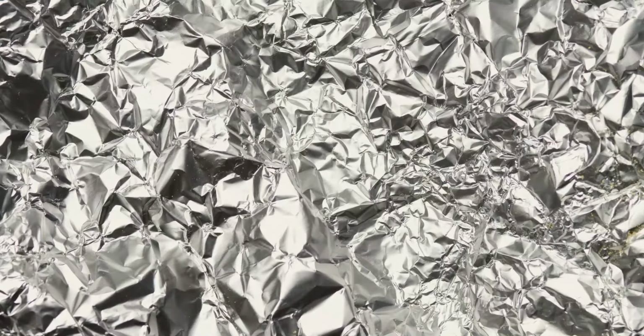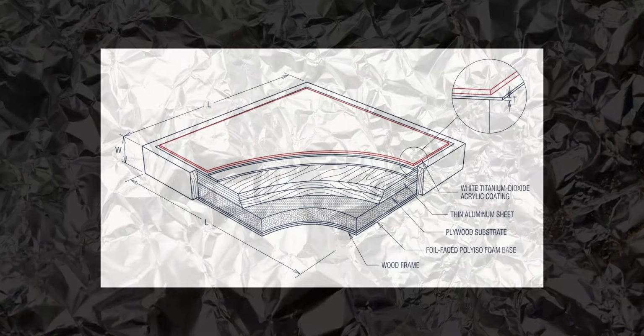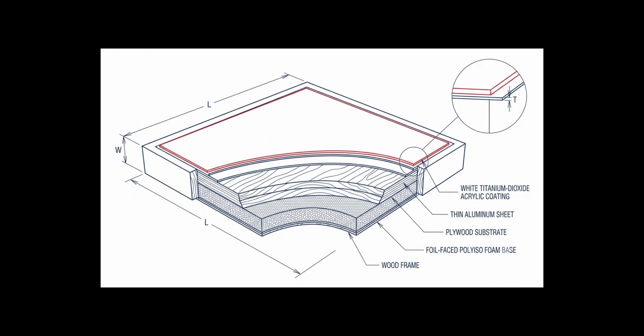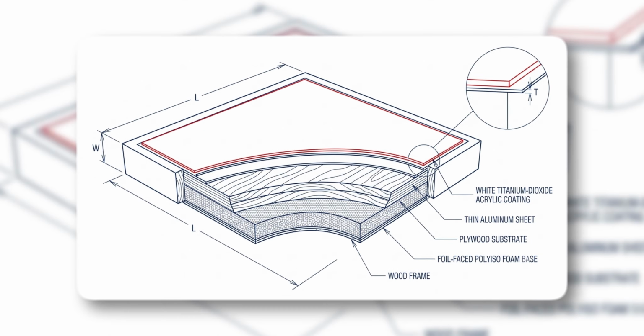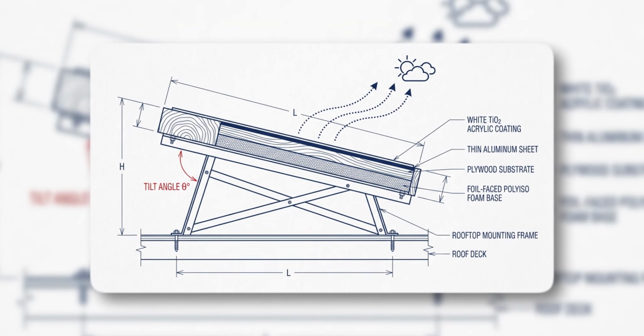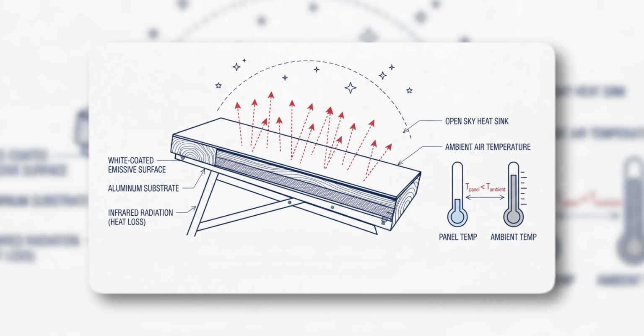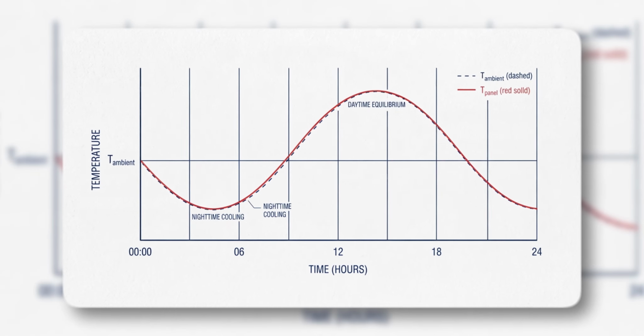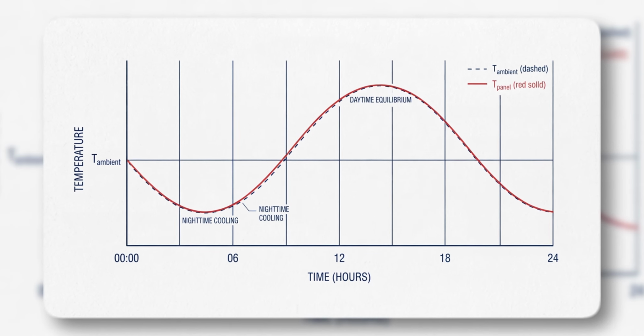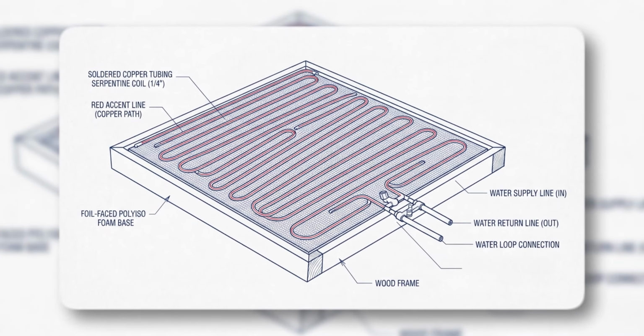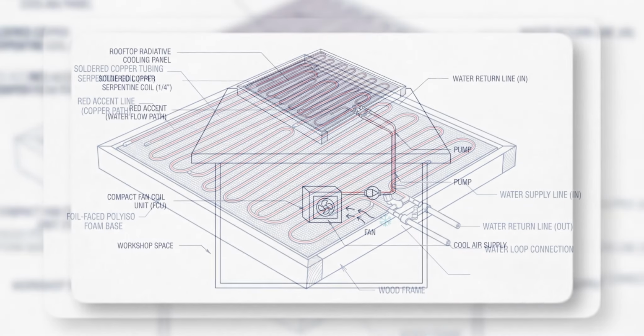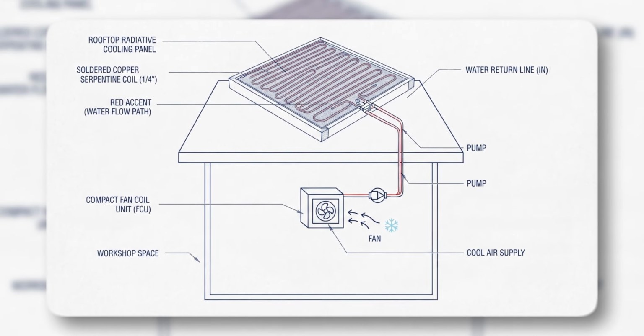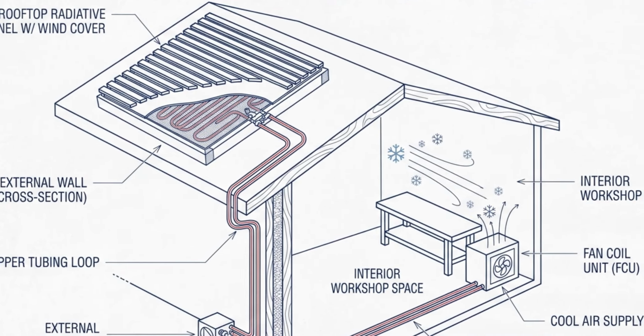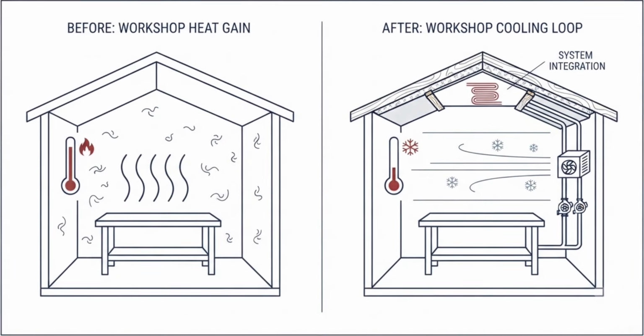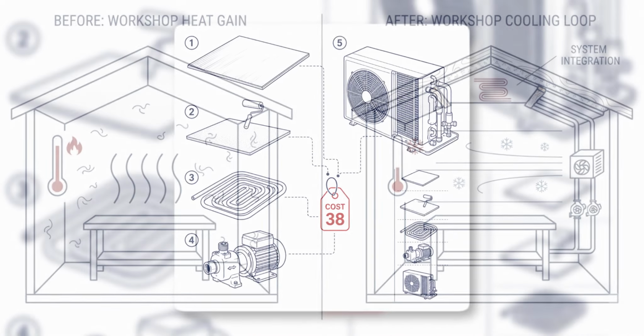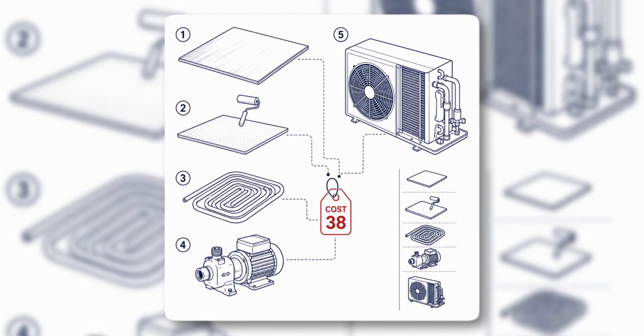He took a 4 by 4 foot sheet of 0.02 inch aluminum from a local metal supplier, coated it with 2 layers of acrylic latex paint mixed with titanium dioxide powder, mounted it on insulated plywood backed with foil-faced polyisocyanurate foam, and angled it up at the open sky. His logged readings showed the panel surface running 4 to 7 degrees Fahrenheit below ambient at night, and roughly at ambient during the day once he added a simple plastic film wind cover. He soldered 1/4-inch copper tubing to the back, ran a small water loop through a fan coil unit in his workshop, and reported noticeably cooler air in a space that used to be unbearable by afternoon. Total cost, $38, including the pump.